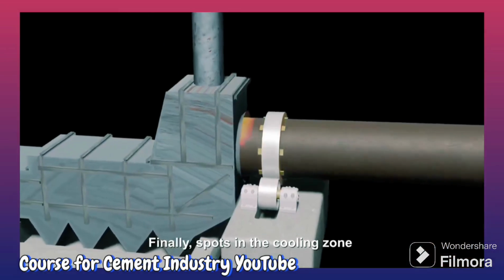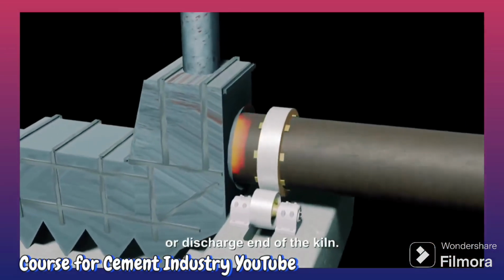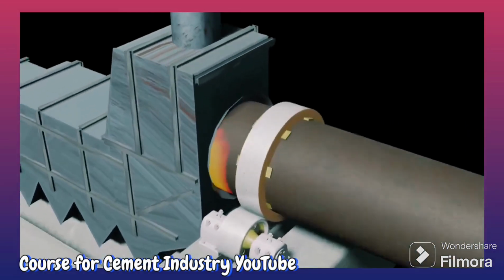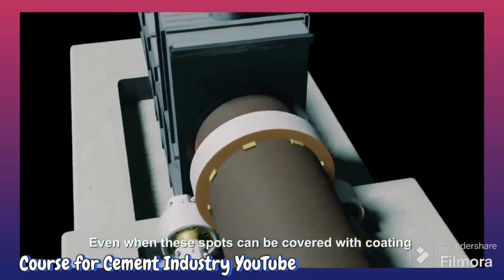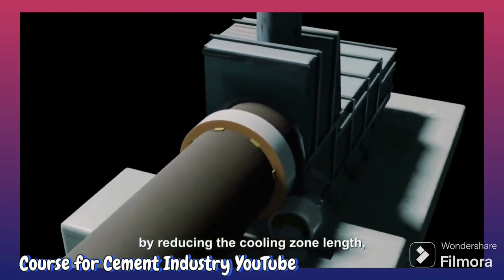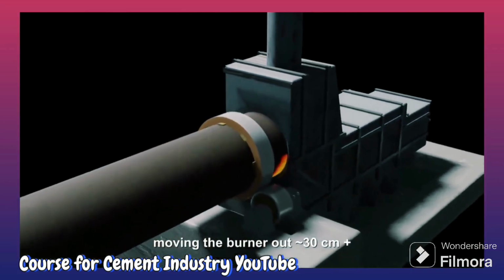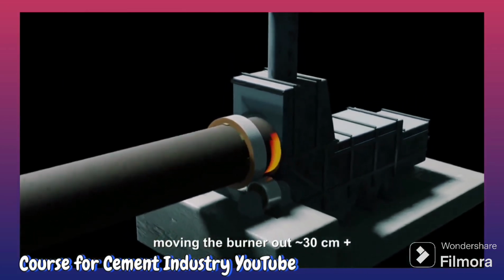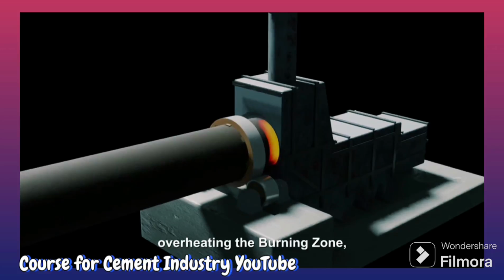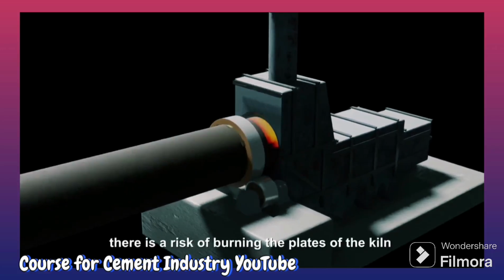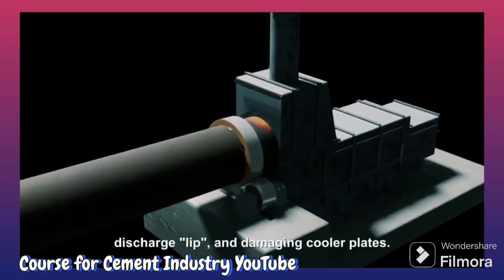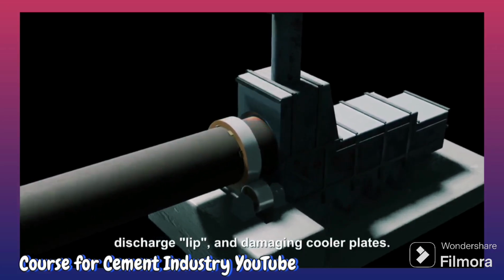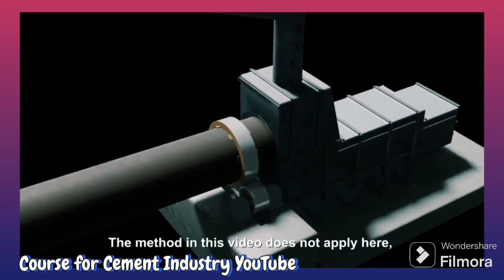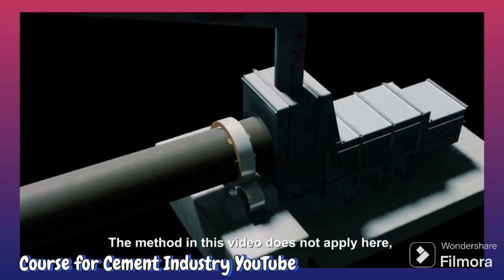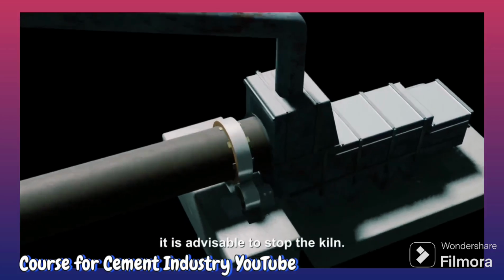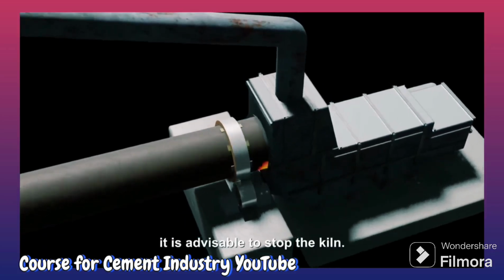Finally, spots in the cooling zone or discharge end of the kiln. Even when these spots can be covered with coating by reducing the cooling zone length, moving the burner out 30 centimeters, and overheating the burning zone, there is a risk of burning the plates of the kiln discharge lip and damaging cooler plates. The method in this video does not apply here. It is advisable to stop the kiln.